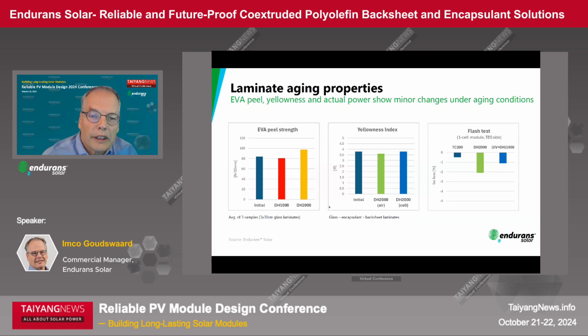And this is for the laminated samples. So we laminated the transparent backsheet and tested EVA adhesion retention there in damp heat. And on the right side, we made mini modules with just one cell, and we also checked the degradation after damp heat and combined damp heat UV, which is still well within the limits of what is acceptable. Next slide.